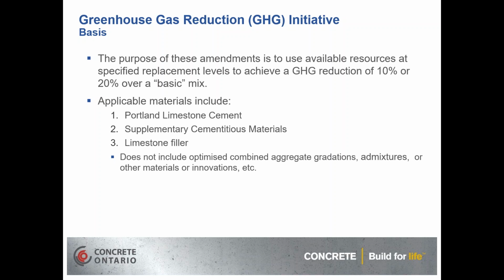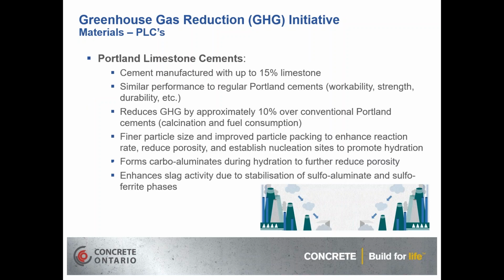So the materials that the MTO identified as being applicable to this are Portland limestone cements, supplementary cementitious materials such as slag or fly ash, and in some cases silica fume, and limestone fillers. Unfortunately, this does not include other methods of innovation and optimization, such as optimized combined aggregate gradations, admixtures, and other technologies that are out there. So it's a very, very basic outline that they have right now at the moment.